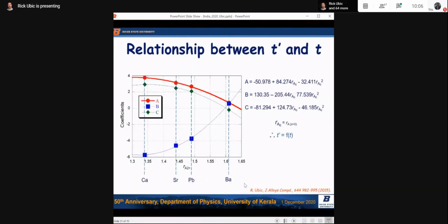I know there are a lot of coefficients in this talk. So we've got to get a fit for the ABC coefficients. They're all quadratics if you graph them with the size of the divalent species when x equals 0. So A, B, and C, we can plug in these values from Shannon, and so we can get T prime as a function of T. Now we can use our model to go forward and calculate lattice constant.